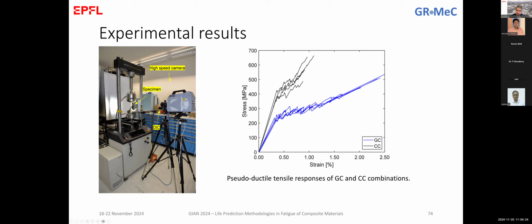The stress-strain curves described here show exactly what we mentioned before about this pseudo-ductile behavior. The black line is the carbon, so high and low modulus carbon materials, and this is the line with the glass and high modulus carbon material. We see that in both curves we have a pseudo-ductile behavior, which is more pronounced in this one, exactly because the difference between the strain at failure in this case is much higher. So this is a very significant effect, because this can help in structures.